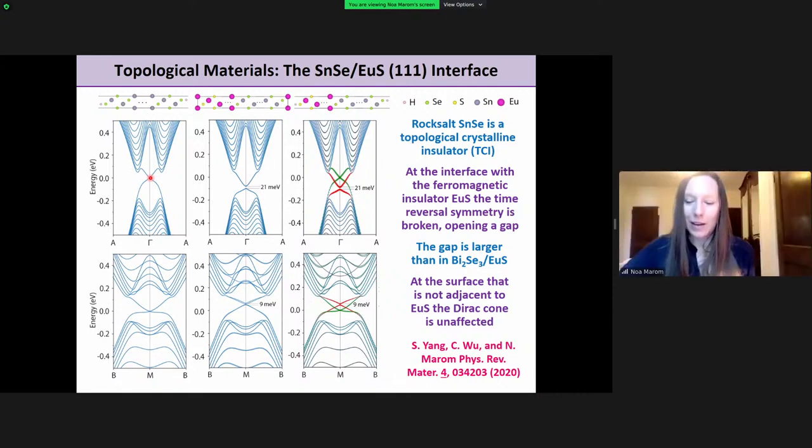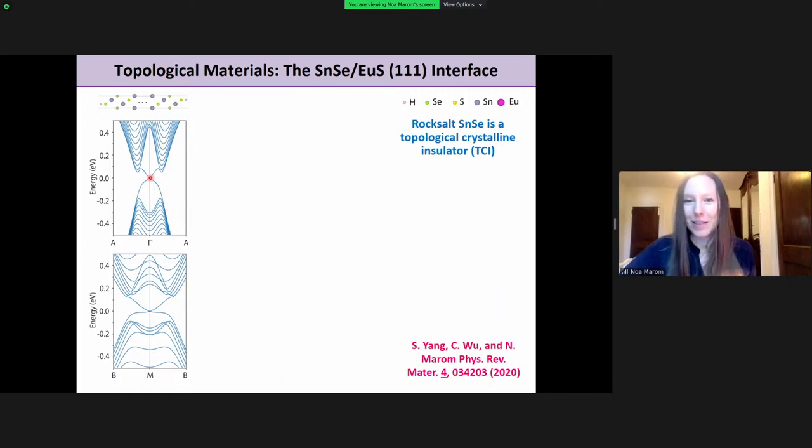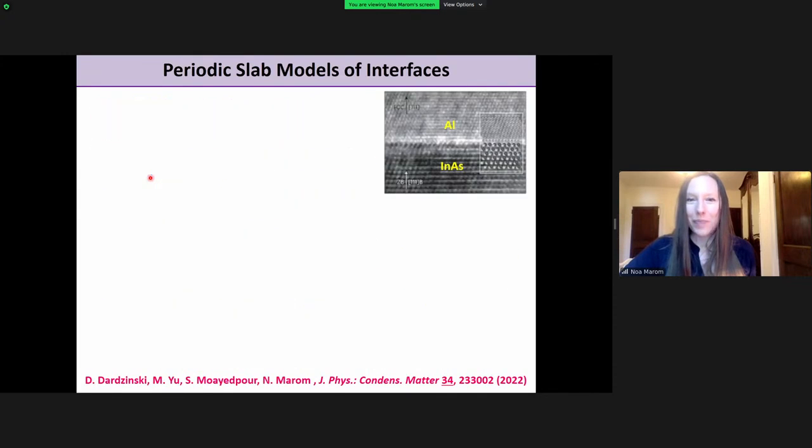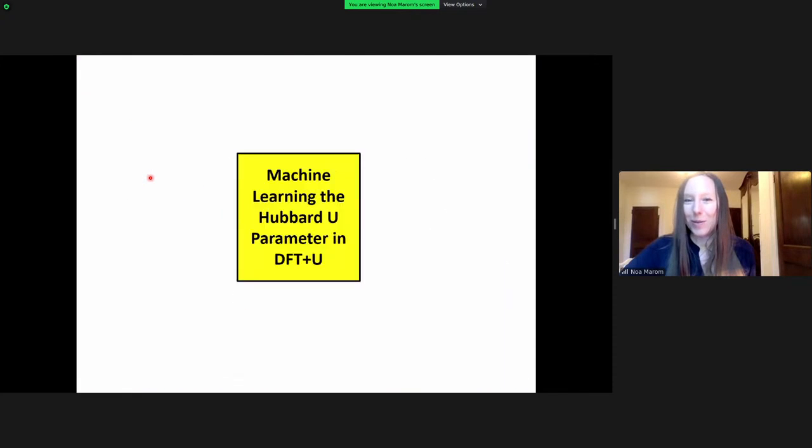So we find that optimizing them separately can lead to a different number of layers than if you optimize them together, which is why we do that. But the surface energy does also go into the interface energy, so we also have to optimize them for the surface energy separately. So basically you have to do optimization for each of the slabs with respect to surface energy, and then with them together in all the combinations, to get a total interface energy that you're sure is correct.